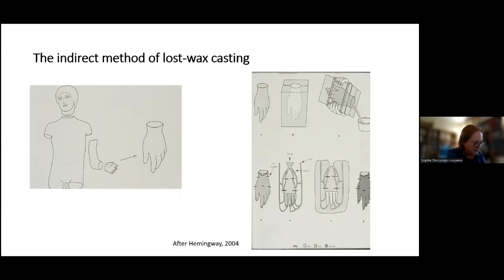which was perfected in the second half of the 6th century BC. This process was based on the prior creation of a model, a prototype, most often in clay. This original model was cut into parts that were to be cast separately, then joined together. The next step was the taking of an impression, that is, the manufacture of a clay or plaster master mold, which was taken from the original model and lined with a layer of beeswax. The wax was poured in, brushed on, or applied in slabs.